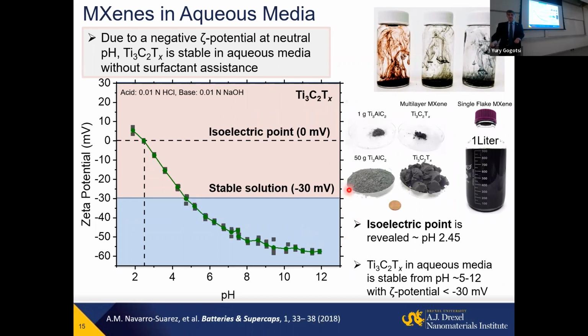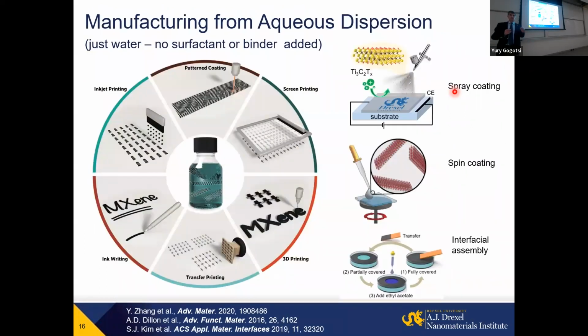So we go all the way from ceramic powder to this type of clay, MXene clay, we call it, because it's really like a clay, containing some water between the layers, two-dimensional OH-terminated, oxygen-terminated flakes, to colloidal solution. You can see here a liter bottle with typically 10-20 micron flakes. But you see also they have different colors. Unlike graphene, I'm comparing to graphene because it's kind of the most common material most people know, it's not all shades of gray, those are colorful. But moreover, remember, those are plasmonic colors. I will come back to it later in my talk.